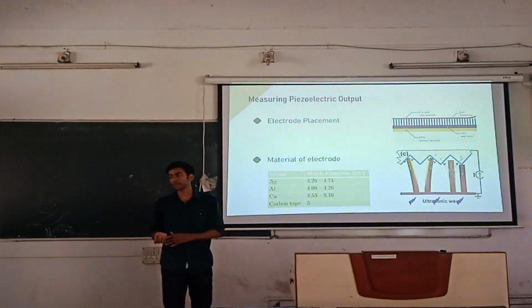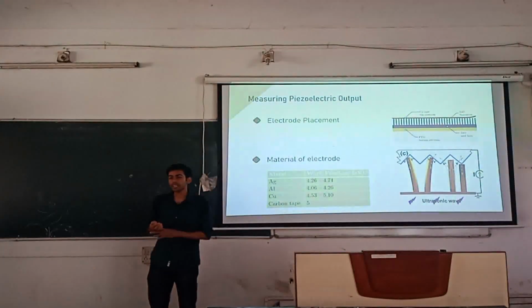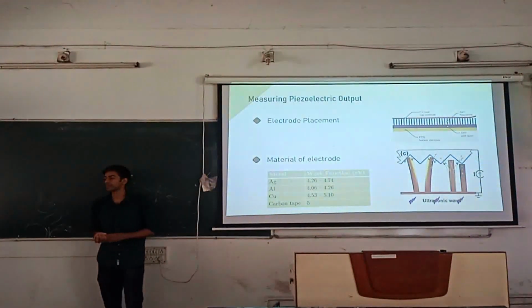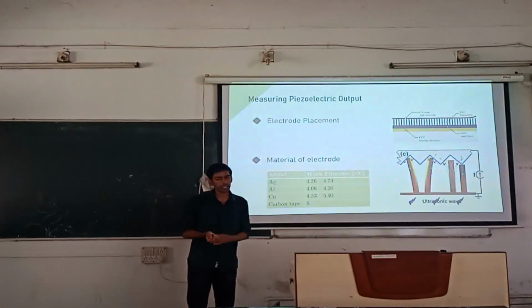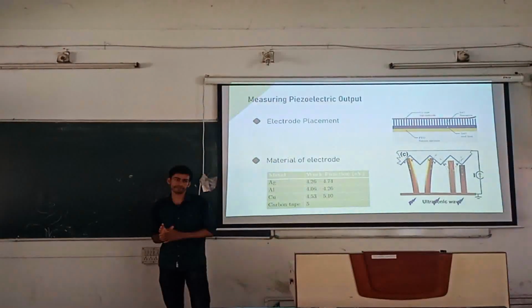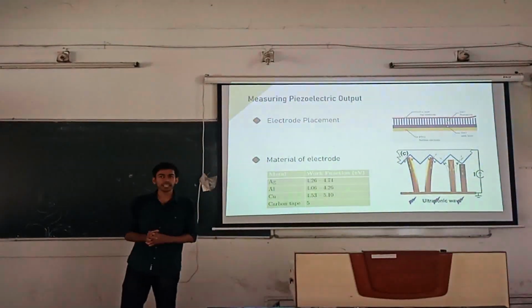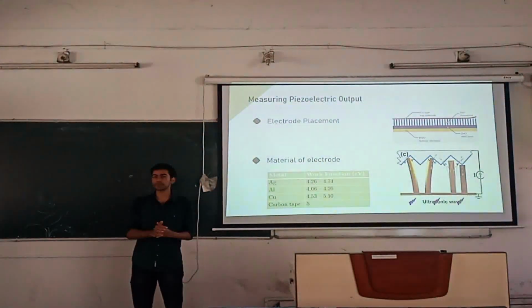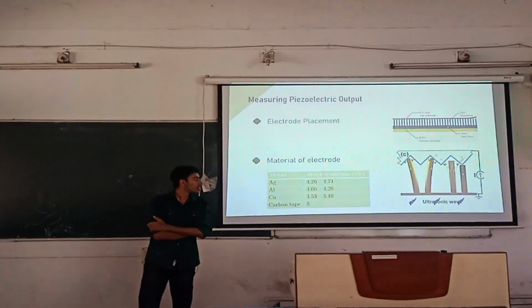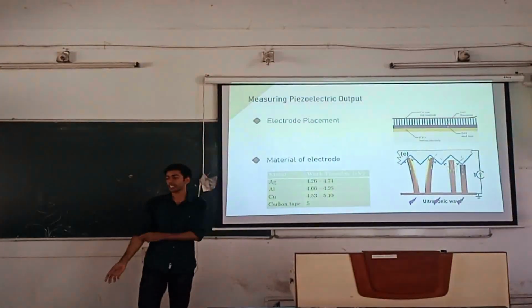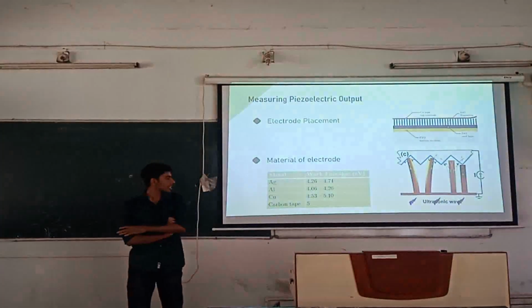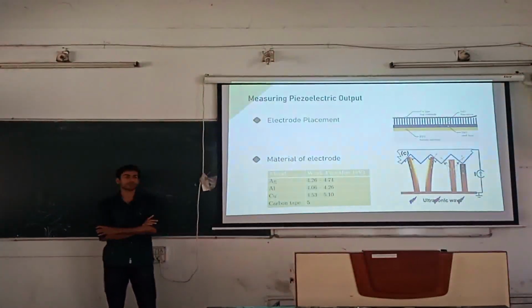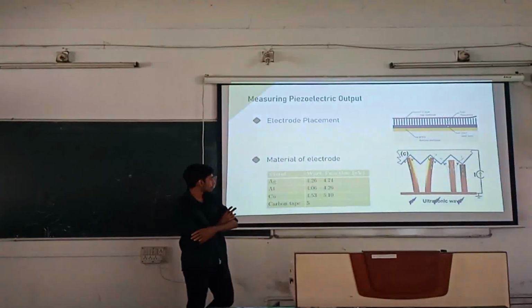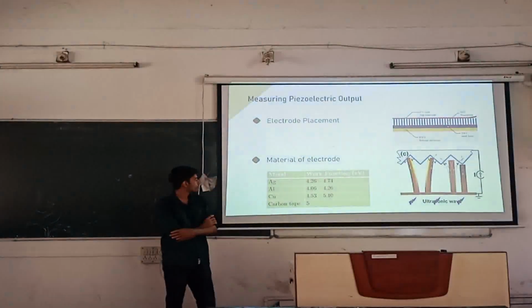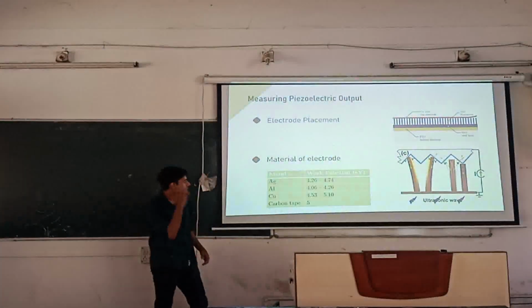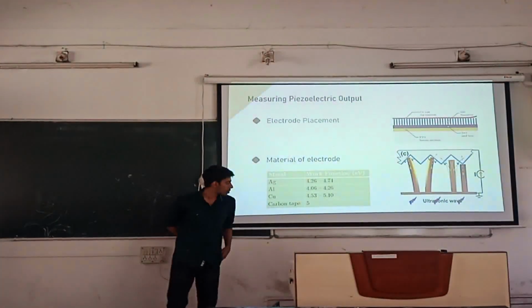Since zinc oxide is a semiconductor and the electrode we are keeping is a metal, the type of junction that forms between the metal and semiconductor matters. By choosing the proper metal-semiconductor junction, we can make sure negative voltages won't go. By choosing a proper Schottky junction, we can make sure the voltage is rectified there itself. So for that, we have to search all the metals and find metals with higher work function than zinc oxide. There are many, but in our lab we have these three: silver, aluminum, copper.